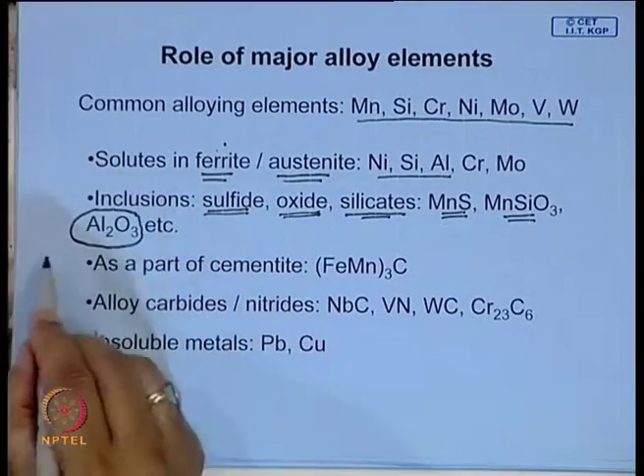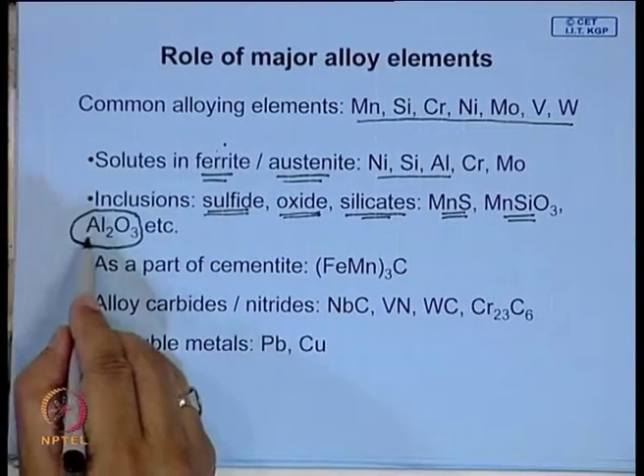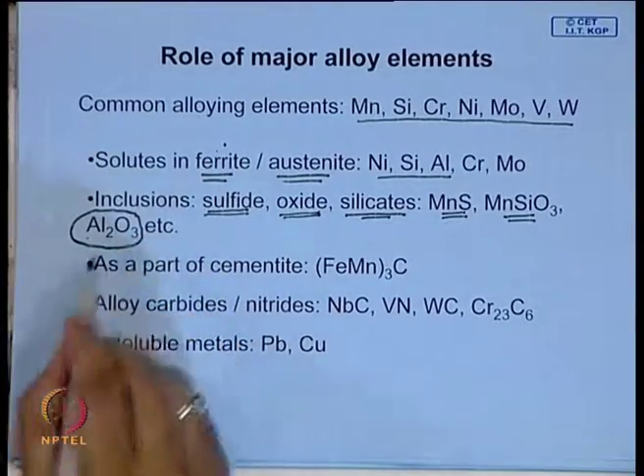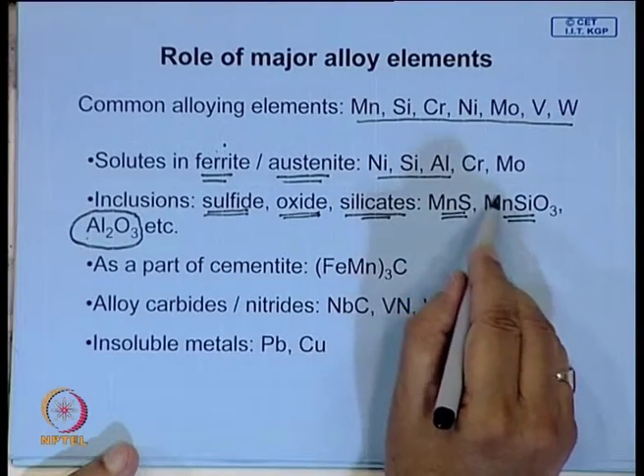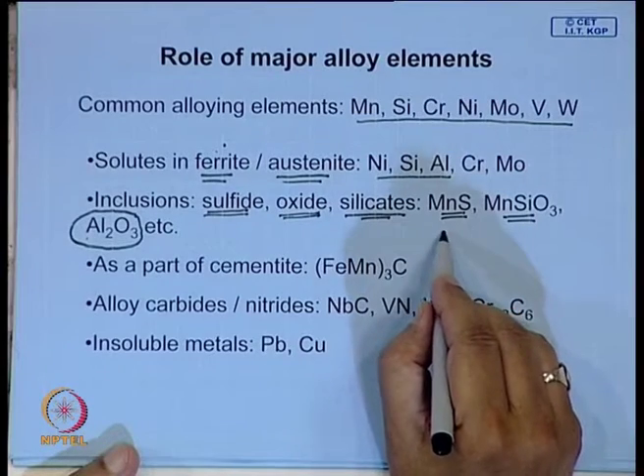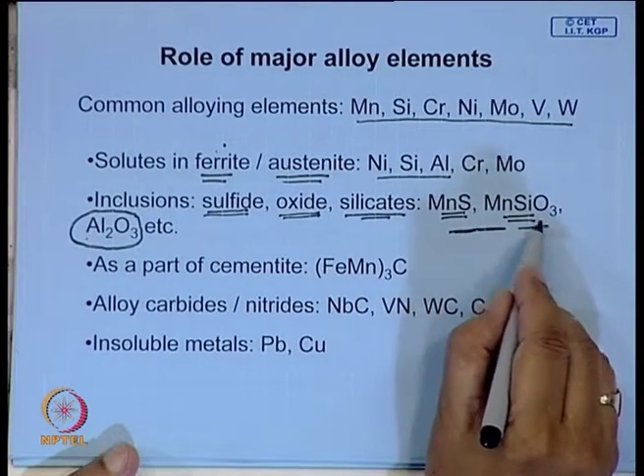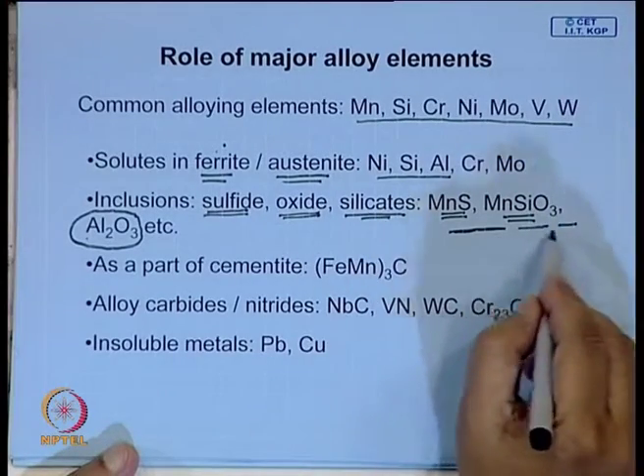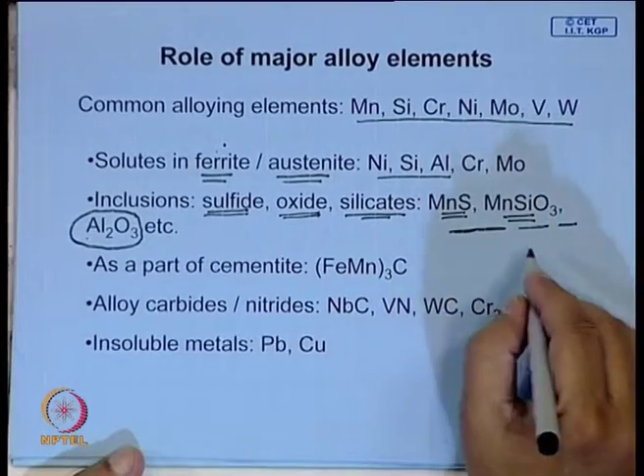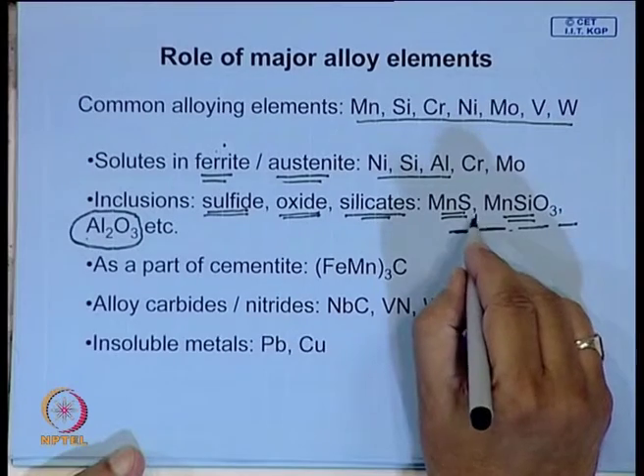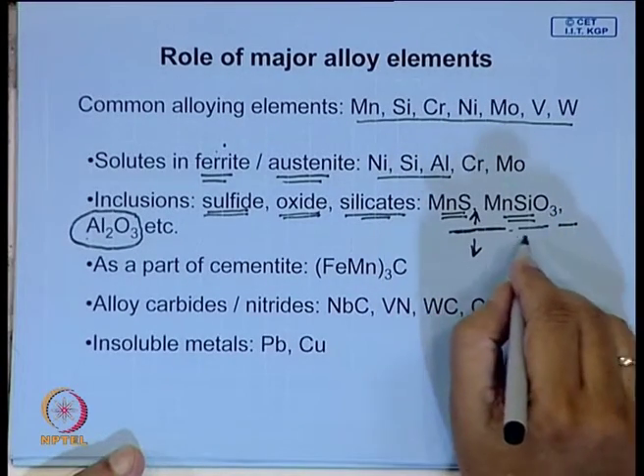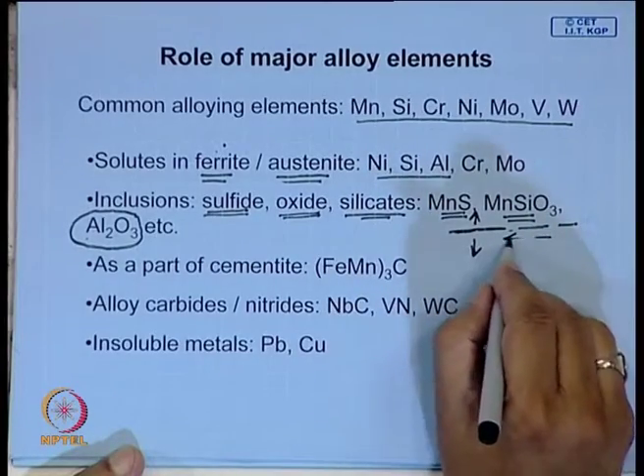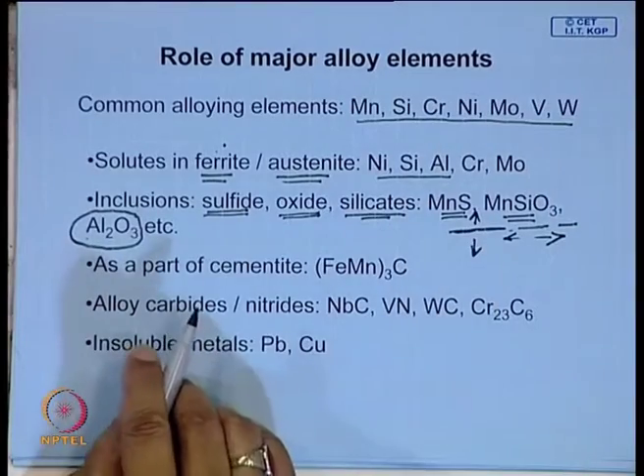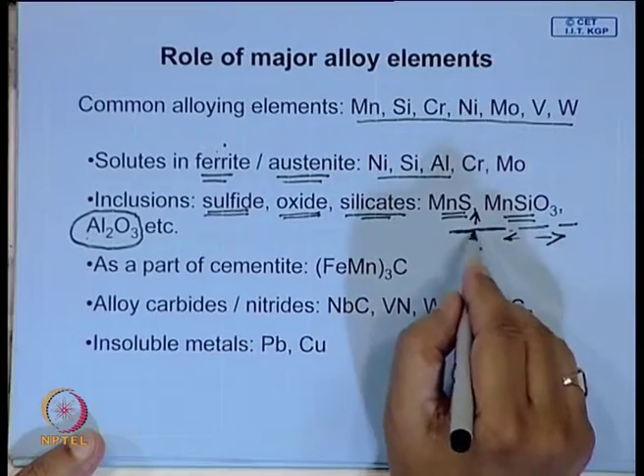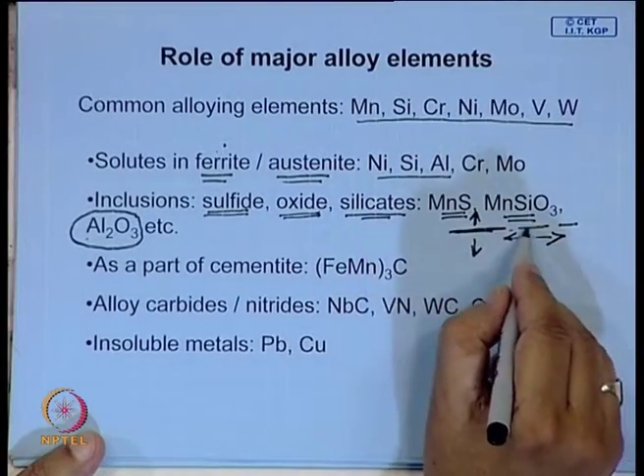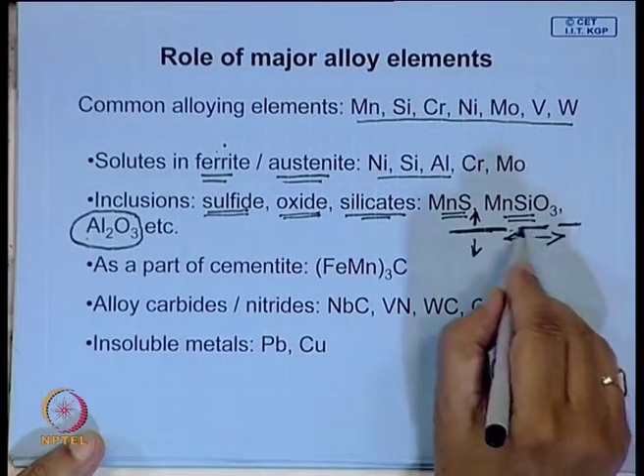Aluminum we have seen is used as a deoxidizing agent and it gives fine grain steel. So, alumina is also an inclusion, and some of these inclusions deform easily during hot rolling. Manganese sulphide, if it is present, will get elongated, as will silicates, and the presence of these elongated inclusions makes the property directional. Suppose there is an inclusion like this, then in this transverse direction it will have lower strength. It will not affect strength along the longitudinal direction, but transverse properties, particularly ductility, get affected. They are also difficult to weld because of these inclusions. They give rise to a defect commonly known as lamellar tearing.